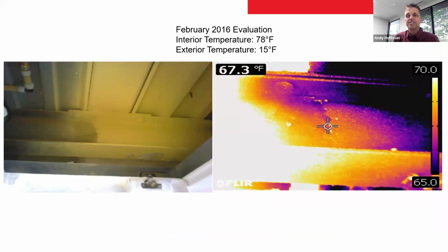So it's 78 degrees in the vestibule, it's 15 degrees outside. The surface temperature of the vestibule you're seeing there with that spot rating was 67.3. Obviously well above what the dew point in that space is ever going to be, which is why in the 8 years now that this has been up and running, they have not had any condensation concerns in that vestibule.